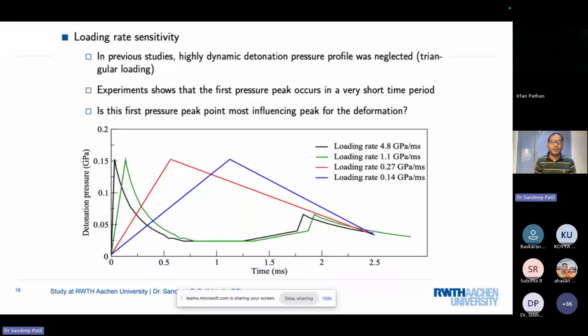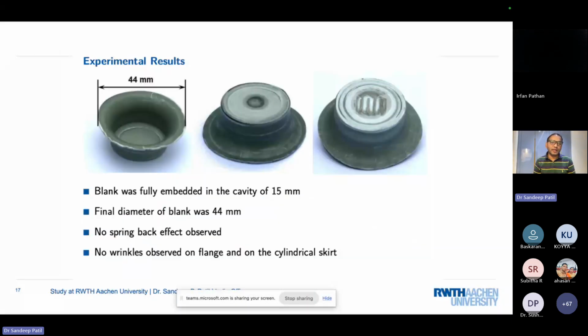What we have seen was that in previous studies, most of them considered the triangular loading. So what you can see with the red line and blue line, they never considered the high loading rate, and this is the first peak, and they were always missing it. Therefore, that was our main focus, to see whether this first peak is the most influential peak for the deformation or not.